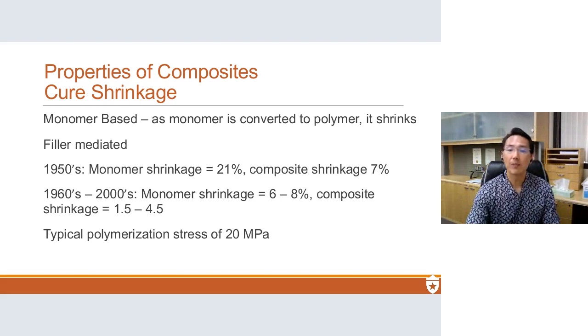Another property is cure shrinkage. I keep coming back to this. This is very important. Again, it's monomer based. We talked about that. It's filler mediated. The higher the filler loading, the lower the shrinkage. In the 1950s, the monomer shrinkage was 21%. Composite shrinkage with powder or just glass filler was 7%. Then with the use of bis-GMA with larger monomers, shrinkage went down to 6 to 8%. And with filler in that, it went down to 1.5 to 4.5%. And typical polymerization stress is about 20 megapascals.